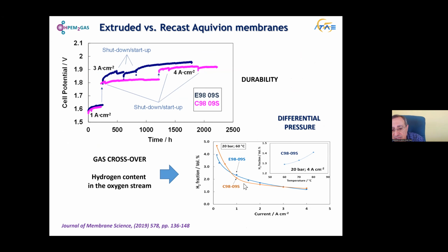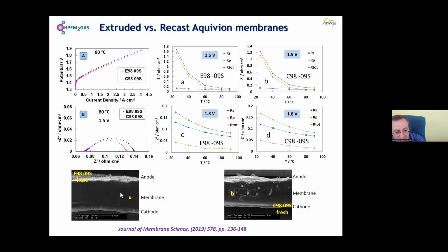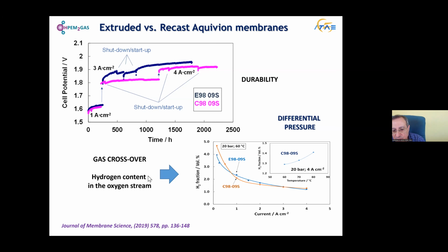Another important aspect to consider is dealing with hydrogen crossover. I have mentioned that the membrane has full density, but in principle there is a possibility, since there are some water channels inside the membrane, you can still have some gas crossover. Regarding the gas crossover, the concentration of hydrogen in the oxygen stream becomes lower when you increase the current density, because you have a lot of oxygen evolving that will dilute the hydrogen permeating through the membrane.